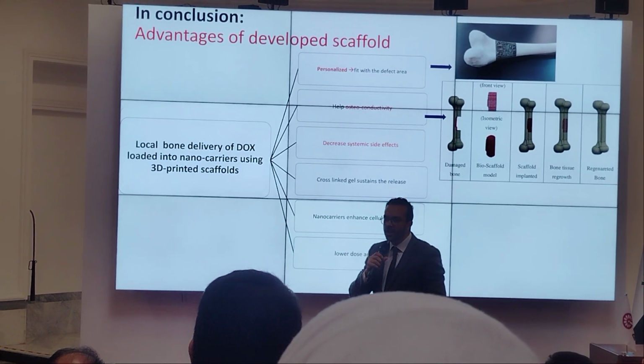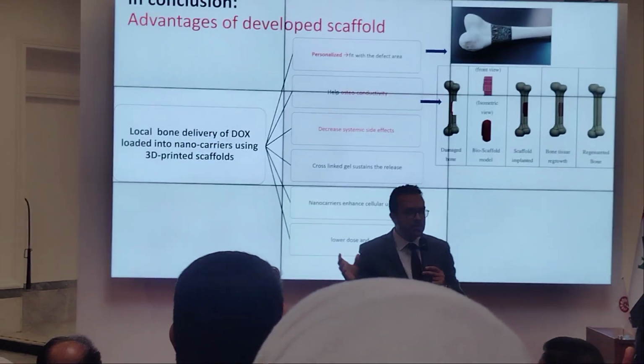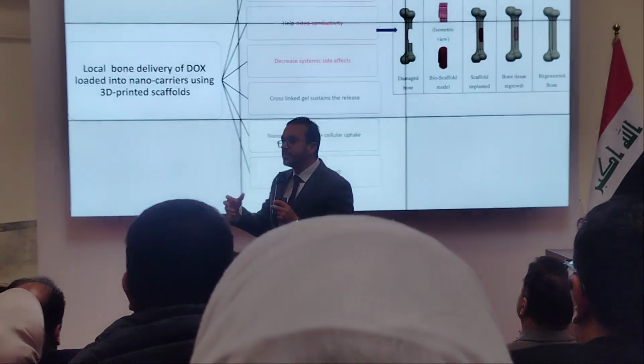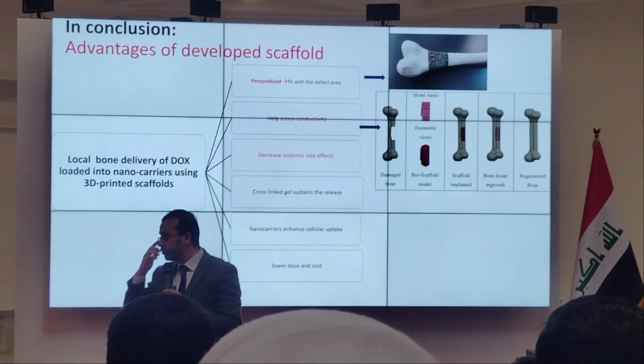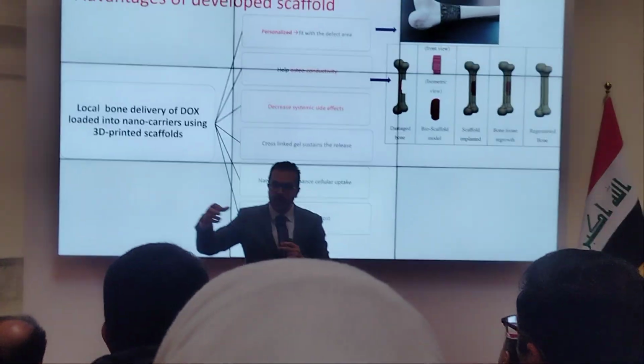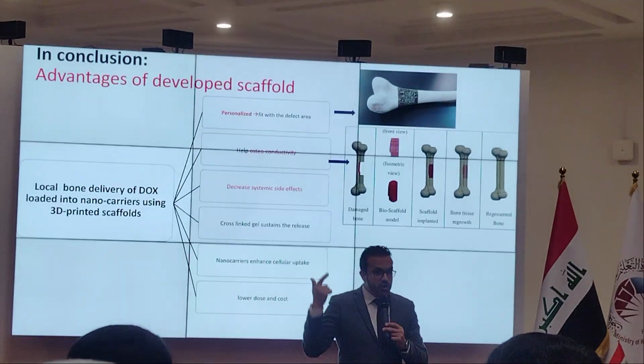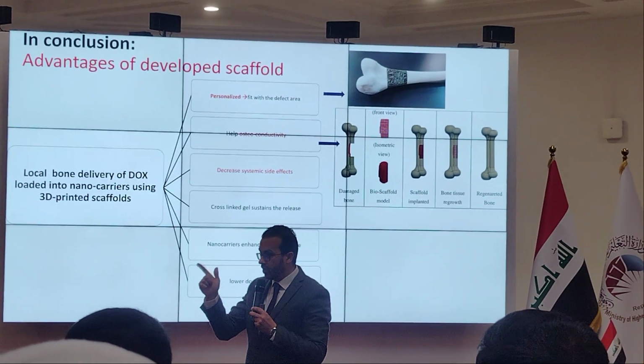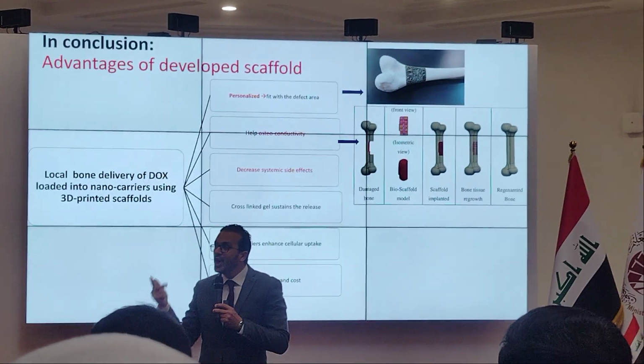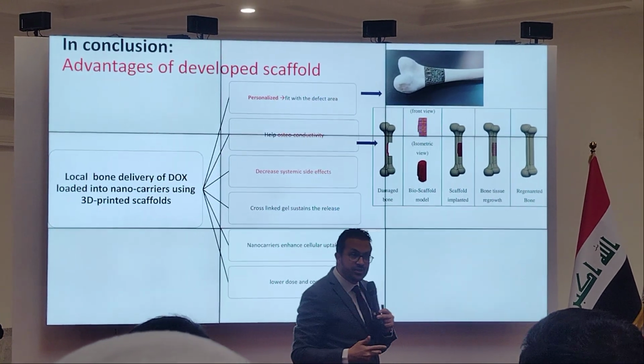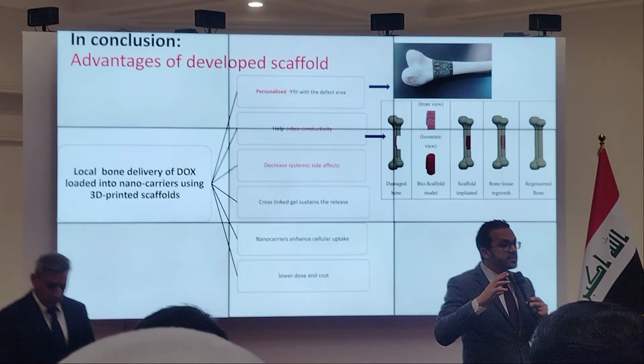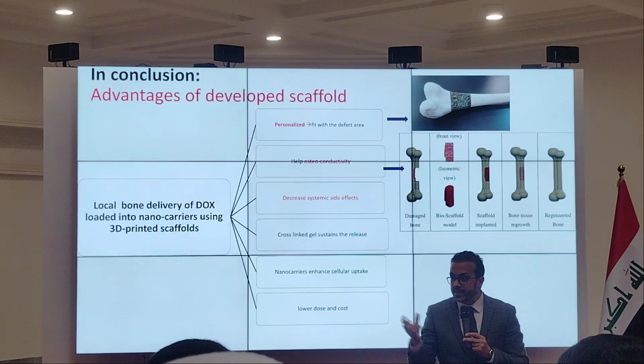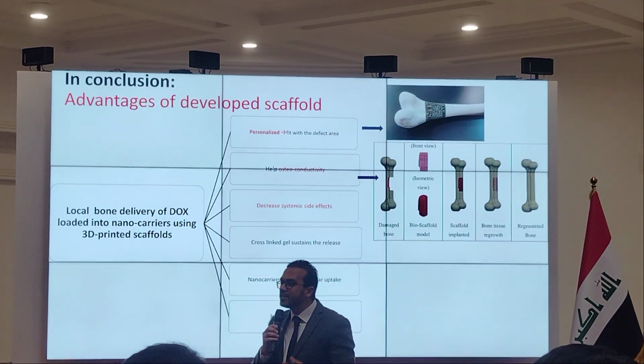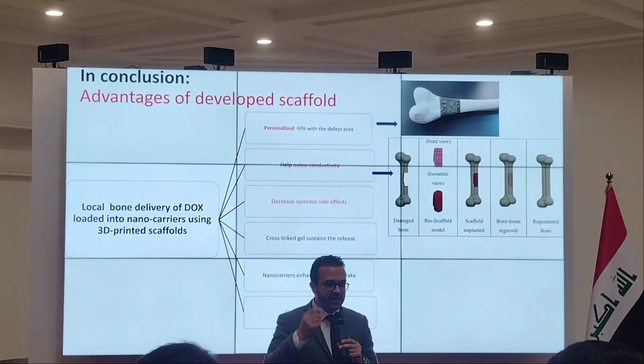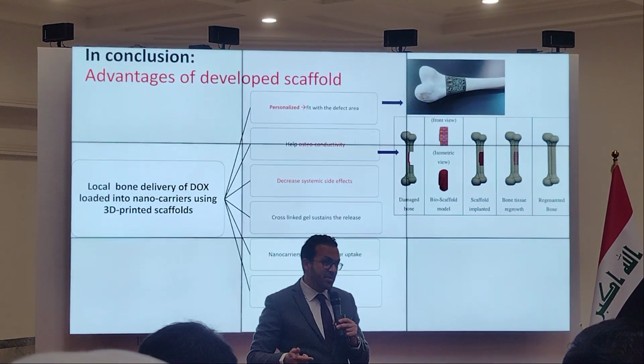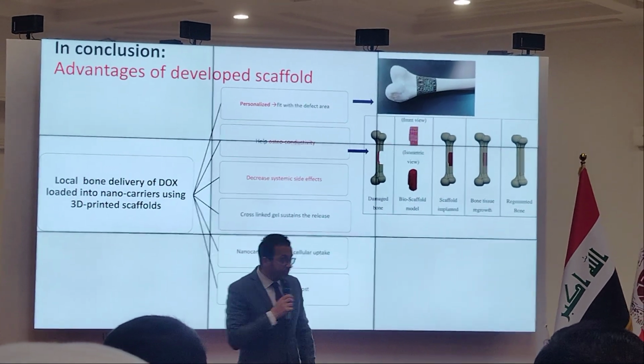So, in conclusion, in our system, using 3D printing technology, we could overcome the main challenges of the available treatment of osteosarcoma. So number one, we will personalize the scaffold to exactly fit the patient. Number two, we will achieve maximum concentration of the drug in bones, avoiding systemic side effects. We could achieve prolonged and sustained release using the cross-linked gel. We can tailor the mechanical properties of the scaffold itself, and of course, we are decreasing the dose, and most importantly, decreasing the cost, because most chemotherapeutic agents are very, very expensive.